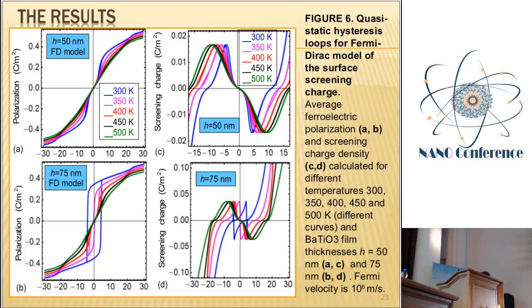The situation with the Fermi-Dirac model is more unusual, which can be expected from the potential relief. First of all, for 50 nanometer films, we see no loop at all. We see very thin double hysteresis loops vanishing. And I know that here is a loop, but you probably see only here the thicker one at 300 kelvins. And nonlinear shape with temperature increase, and an almost linear green curve at 500 kelvins. The same for the screening charge. For the screening charge, we see a nonlinear curve, but without a pronounced hysteresis window.